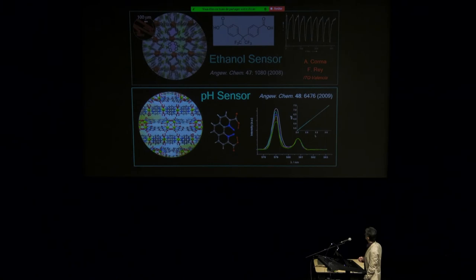And we also made a pH sensor, and that's a sort of layered structure. It's not exactly a MOF, it's a hybrid material with layers. This is the linker, and what is important is that there are two types of local environments for the lanthanide ions. In one case, we have dimers. In the other case, we have monomers. And dimers have OH groups and water molecules in the coordination sphere, and therefore they are sensitive to pH.